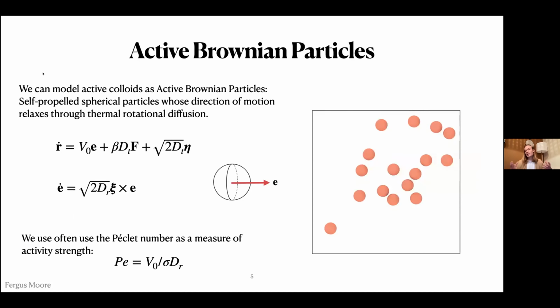If we're going to simulate these kinds of colloids, there's a popular model that's often used, which is nice and simple; it neglects things like alignment and hydrodynamics. We have one particle that self-propels, and the direction of this propulsion rotates with thermal rotational diffusion. So we have the equations of motion here. In the velocity, the first term, V0 is a constant speed, and the direction e rotates with thermal diffusion proportional to the rotational diffusion coefficient, with a random Gaussian noise. Then we have interparticle forces, and finally a Brownian noise term with translational diffusion and an independent random Gaussian noise term.